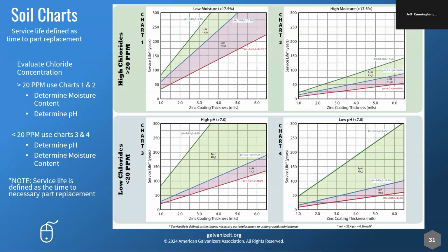Once you have determined the primary and secondary factors of the soil you're using, you can figure out what chart you're on. So say we're working with low chlorides and a high pH. We're going to be on chart 3. Once again, right around 4 mils of zinc on the piece is acceptable to ASTM standards. Still, anything in the red is going to be less favorable, anything in the green more favorable. So still red, you're looking at plus 70 years or whatnot. Feel free to use these on our website. If you go to our website and just search soil charts, they'll show right up for you as well.